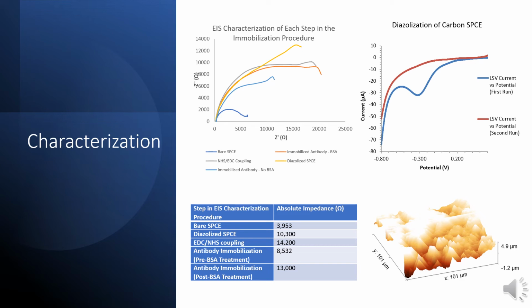This is important because the diazonium salt is light sensitive, and improper LSV scans likely indicate that the diazonium salt has degraded. In the top left, each of the electrochemical impedance spectroscopy was taken at each step of the immobilization procedure, and the absolute impedance values were calculated using a best fit circuit and can be seen below.